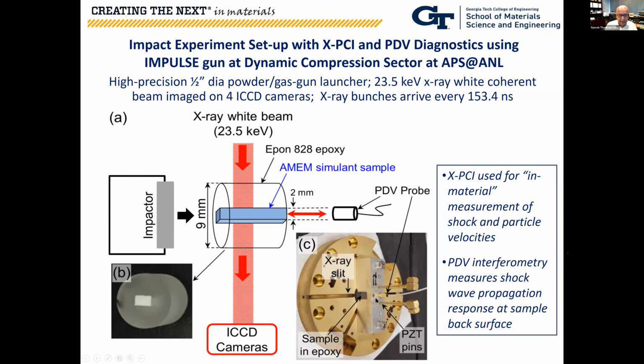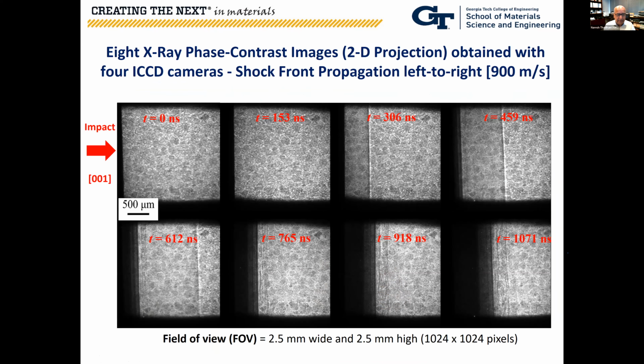There are 2 diagnostics used simultaneously. After impact, everything is timed so X-rays penetrate through this 2 millimeter thickness and give us 8 snapshots at different times of what's happening in the material as the shock propagates through the 9 millimeter length. Simultaneously, we put a photon doppler velocimeter probe at the back of the 9 millimeter sample to monitor a free surface velocity profile at the back—that's a backup diagnostic that can come in handy.